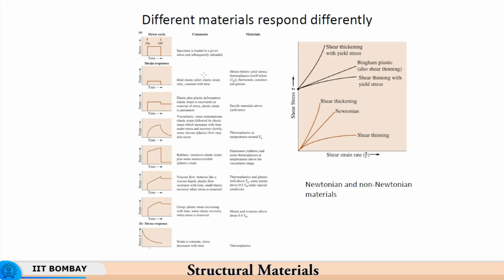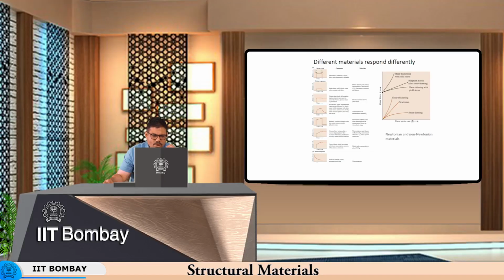So, take two materials, let us say aluminum and copper, and nickel. All of them have a face centered cubic structure, but because of the difference in the interpotential curves, they would respond differently to the same stimulus, namely the same variation in the stress. Here the variation in the stress is on, constant, and off. The ideal elastic solid would show an elastic strain in tune with the increase in stress.